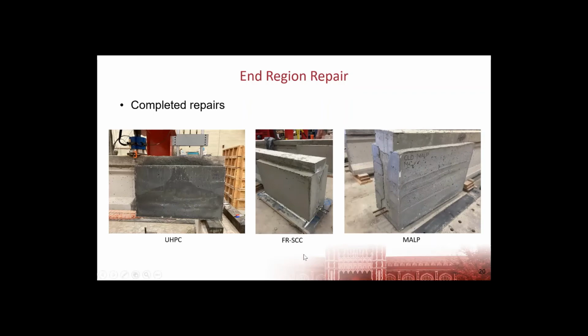For the MALP on the right, we were mixing individual batches of a bag of material and a bottle of activator at a time, which is the process recommended by the manufacturer. That resulted in a number of different batches. Again, it sets really quickly, so you can see these pour lines in between the layers. We allowed it to flow under the beam and then started alternating sides in terms of casting the material. Because this chemically bonds to itself, we didn't anticipate the pour lines being an issue. That was an expected result. It just doesn't look quite as nice as the other two because of that.